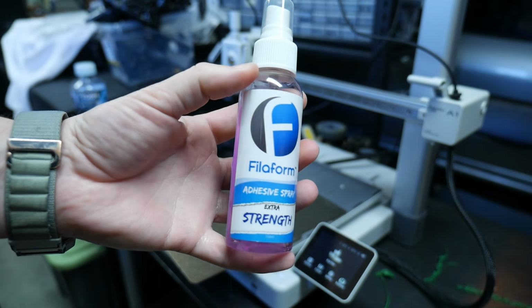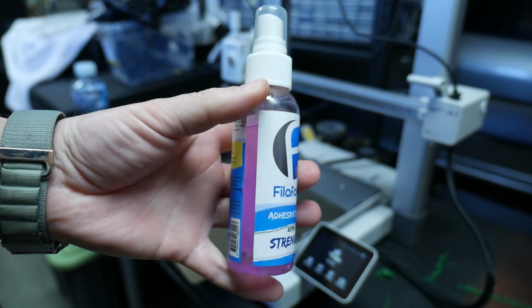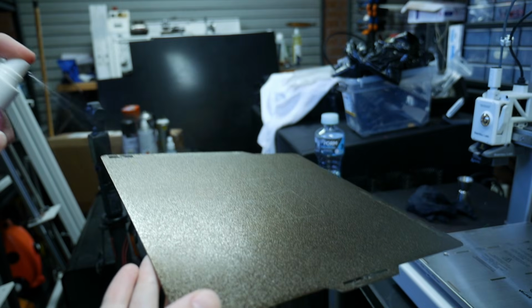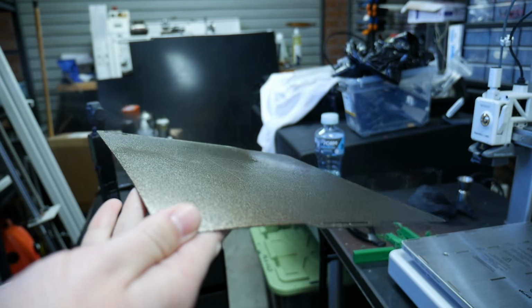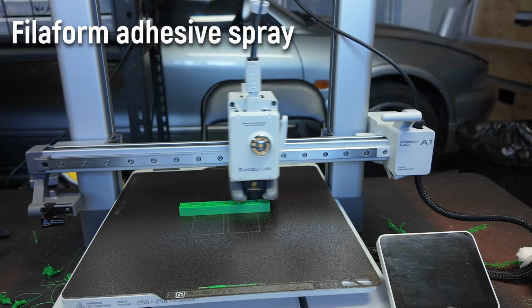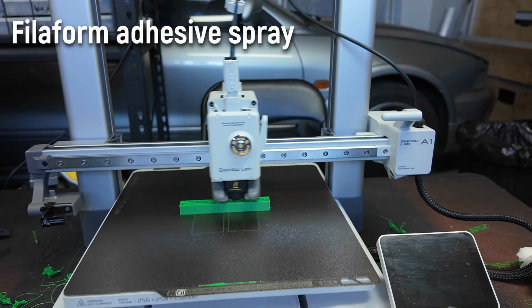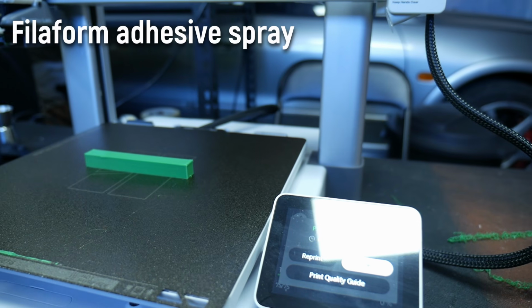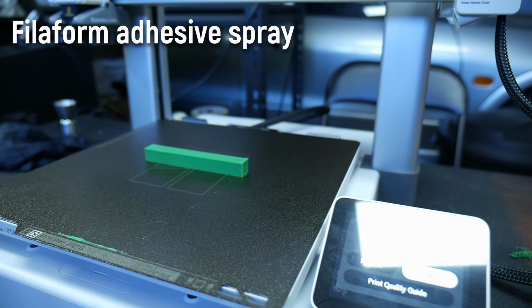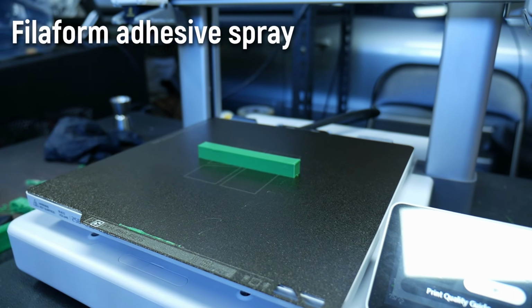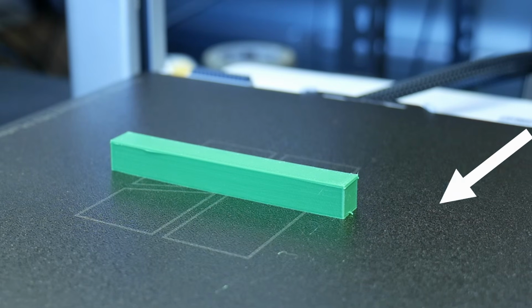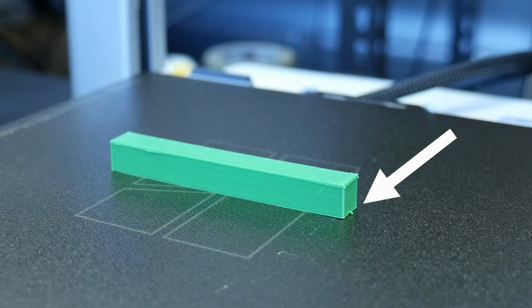As a sanity check, I cleaned the print bed one last time and gave it a spritz with this bed adhesion spray from Filaform. This is their extra strength version. Not sponsored in any way, they sent this to me ages ago to try out, and well, yeah, it works really well. It stuck the ABS print down with no issues at all, and once the print's complete, you can actually hear the print cracking free from the bed as it cools and contracts.